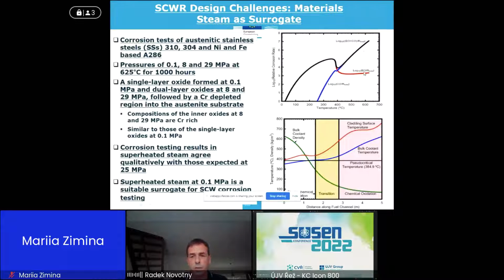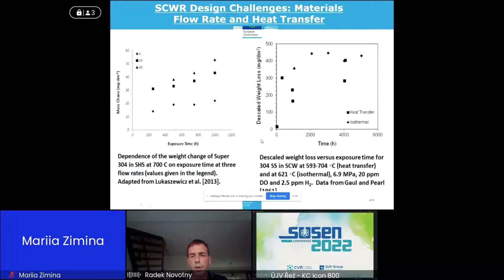If we go along the fuel cladding surface, we can see that we don't have an isothermal situation. We have pressure and temperature development, as you can see in this red curve. And this is another effect we need to study, because most of the tests we have been doing are isothermal tests. We are testing coupons at one temperature, at one set of environmental conditions. But this is very far from the real case. In the real case, the temperature ranges from 300 up to 600, even 700 degrees C. So we have a dynamic thermal situation, heat transfer along the fuel cladding, and we need to know what the consequence is for corrosion or SCC.